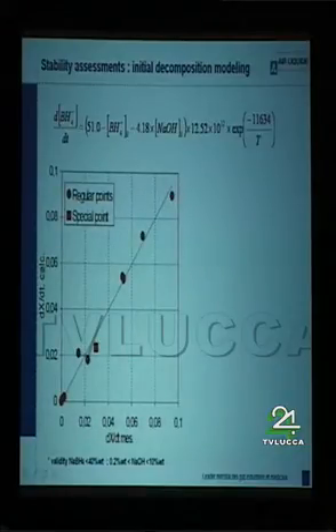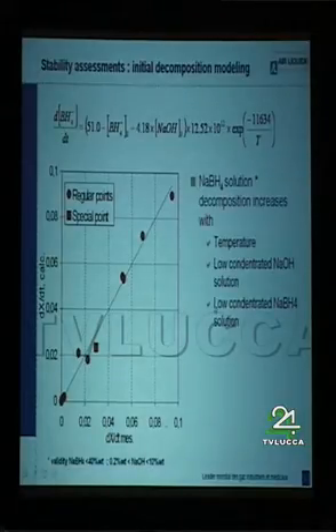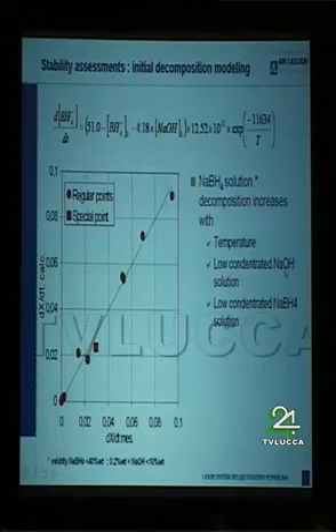If we compare the calculation of the slope with the measurement, we have a good accuracy between the theoretical equation and the measurement. This is a special point which was out of the hypothesis of this equation. This is valid for NaBH4 concentration lower than 40 weight%, for sodium hydroxide concentration higher than 0.2 weight% but lower than 10%. So, as we could predict, NaBH4 solution decomposition increases with temperature, low concentrated NaOH solution, and low concentrated NaBH4 solution.